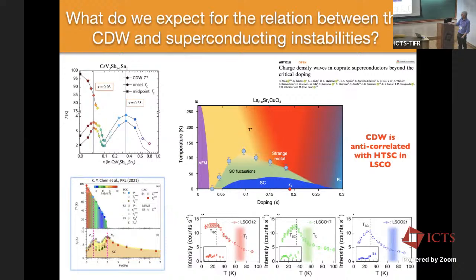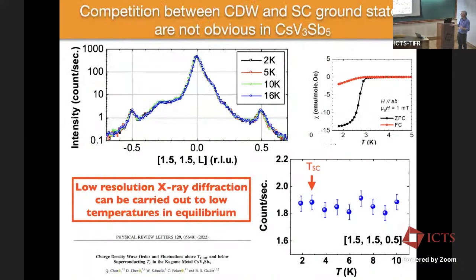Here's something that might be easier to interpret because it's just hydrostatic pressure. And again, the superconductivity goes up and the CDW goes down. So this would also, if you're going to interpret it at all, suggest that they compete with each other. But in our case, in our measurement, which is here, there's no obvious competition between the two.